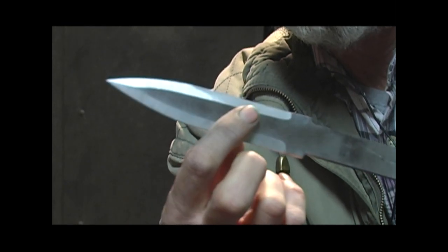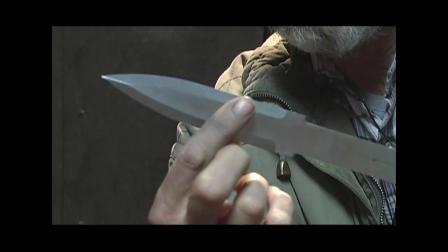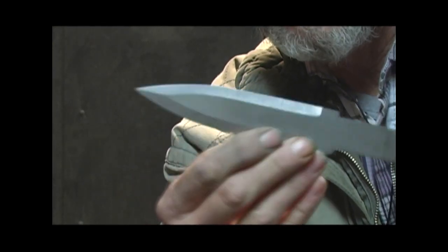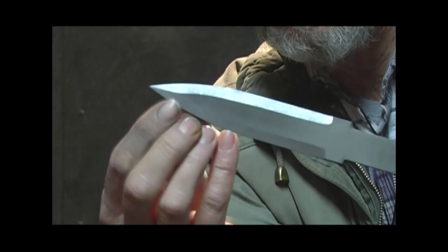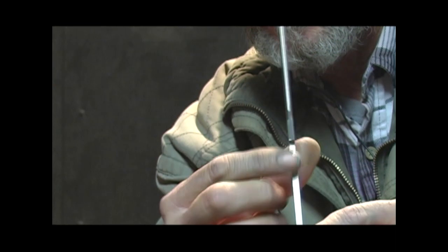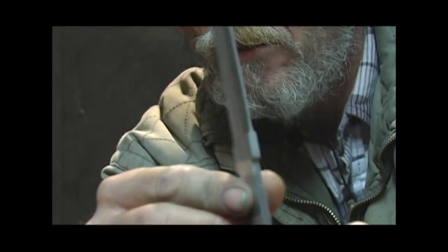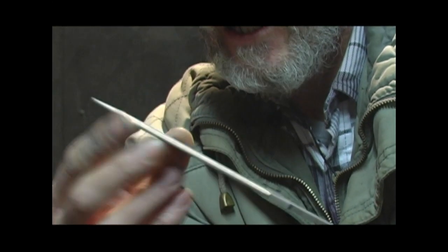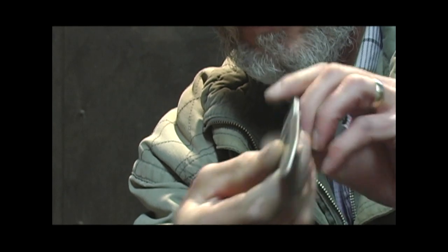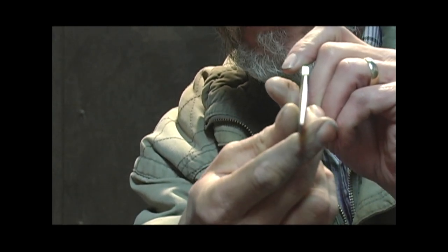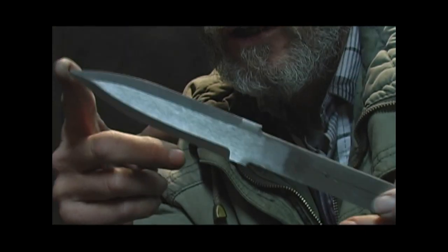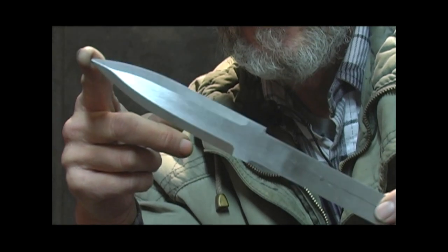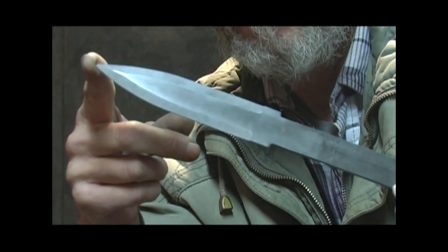See, my grinds are evenly spaced from the center of the flat of the blade to the edge, or 1/4 inch grinds on each side. Come to a nice centered point on both sides. My grinds are even here. You can see where they meet the ricasso, that's a nice even spacing there. My center line on the edge is clearly visible down both sides, so I know I've taken both sides in an equal amount and got my grind nice and centered down the blade. And I've checked that it's straight and even. So that is the rough grind. After heat treating, I'll come back and start grinding again and do the finish grind.